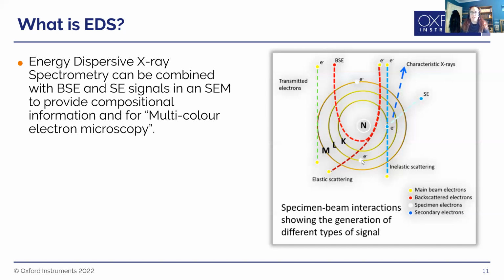So electrons from outer layers will jump down into that space left by the inner layer electron. And in order to do so, they need to release energy, and that tends to be in the form of characteristic X-rays. They're characteristic because the energy difference between these layers can be measured and can be used to identify the atom from which the X-ray originated. And you can see the layers are labeled K, L, M. So when we've got an electron jumping from the L layer to the K layer, that's a K X-ray. So we're able to detect not only the atoms, but the layers from which the X-ray originated.